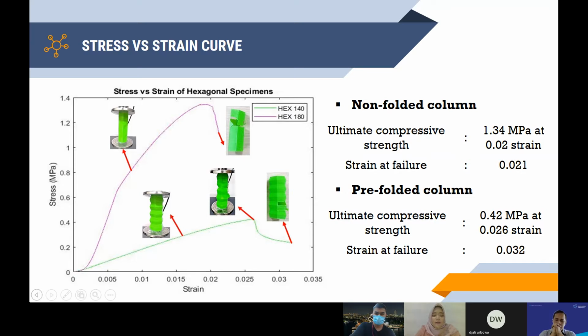However, when the pre-folded pattern is introduced, a significant change is exhibited. The stress is not increasing as quickly as the non-folded one. It increases slowly until it reaches the ultimate strain at 0.026 strain, and then drops significantly to 0.032 strain. From these two curves, the ultimate strain changes from 0.021 strain to 0.026 strain. In other words, the pre-folded pattern shows more deformation.